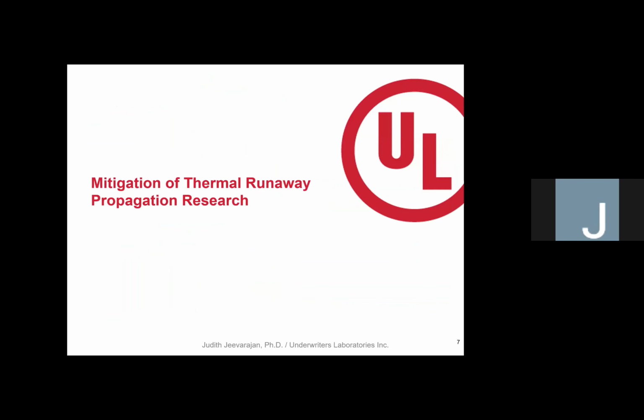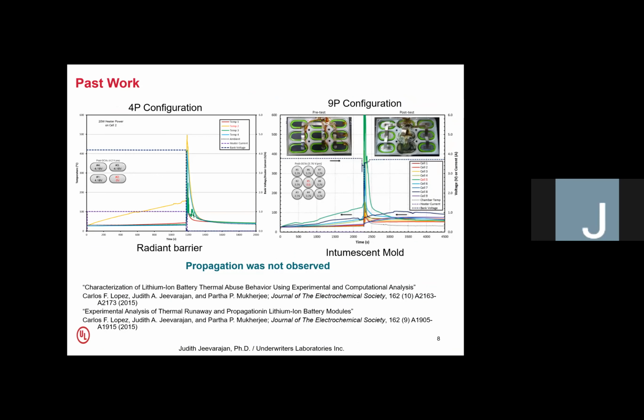So the research on the mitigation of propagation, early on, this was in the 2013-2014 time frame. This was again work done with Dr. Mukherjee and his student when he was at A&M. Carlos was my student intern when I was at NASA, and we worked on materials to see if we could prevent propagation. These are very preliminary studies. We looked at a radiant barrier that was a material 7 layers thick, and it had metal mesh, but it also had ceramic type material on the outside. And like I said, there were 7 layers of it. What we found is that if we placed them between cells, it actually prevented propagation of thermal runaway.